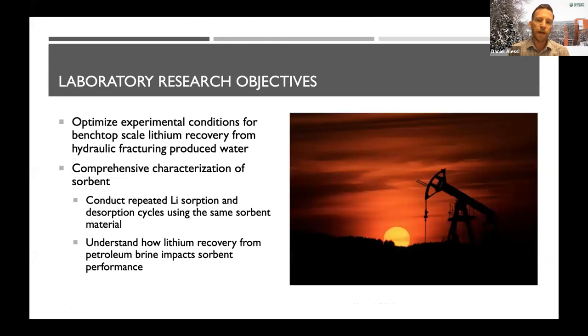So with that background in DLE, we wanted to optimize this particular material at the benchtop. So we're doing laboratory research here, sort of fundamental research, for lithium recovery from, in this case, a produced water from a hydraulically fractured well, but it could be any brine really, even a non-petroleum brine. And to do that, we conducted repeated lithium adsorption and desorption cycles. In other words, we reused that material I talked about many times.